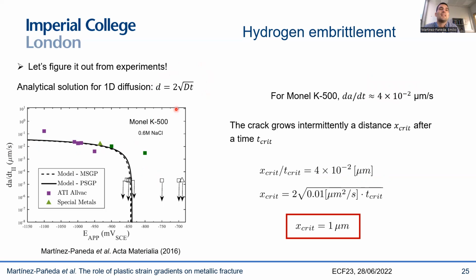And then we know the analytical solution for the diffusion of hydrogen atoms. That depends on the diffusion coefficient and the time. We effectively have 2 equations that we can solve very easily. That gives us the critical distance, the jump of the crack, and how long we need to wait for the hydrogen to reach this critical distance. For this specific case, knowing the diffusion coefficient of the material and the crack speed, we can solve the system and get a critical distance of 1 micron.